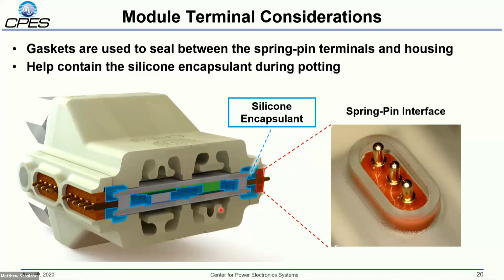So this silicone gasket helps with that. It also helps to keep debris out of the encapsulant. The encapsulant can result in a bit of a sticky or tacky surface, which can pick up dust and particulate from the environment. And those can cause insulation concerns around the module.